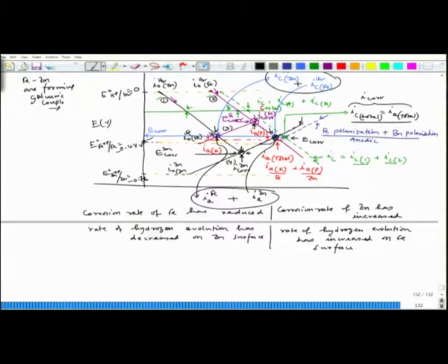This is an important observation. That means the hydrogen evolution or the hydrogen reaction on zinc surface has decreased, whereas hydrogen evolution on the iron surface has increased.